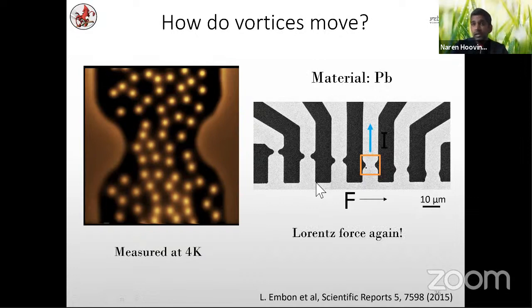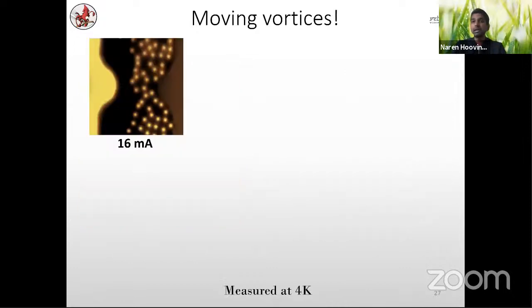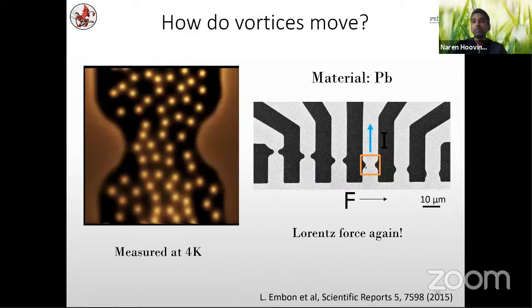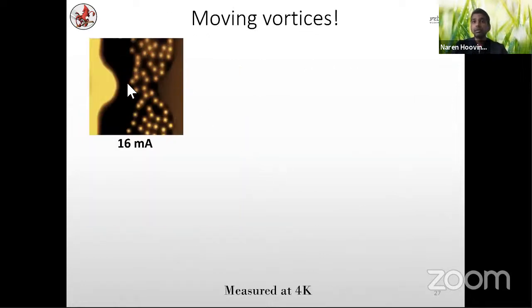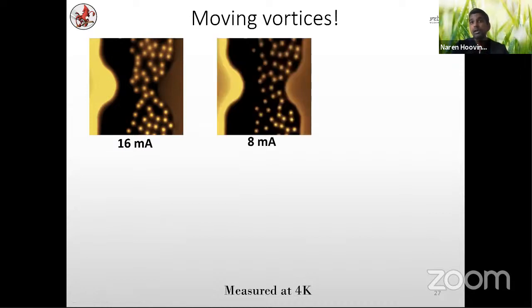And so then you need extra force. So there is a certain pinning force. You can quantify how much energetically favorable it is for a vortex to sit at a certain site by the pinning force. So basically, if you apply a certain current, you need to create enough Lorentz force for the vortex to be moved out of a pinning center and then move to the next one. So basically that's what happens in this experiment, where we apply a current as well to the static vortices. And you can see that the vortices start moving to one end. By that I mean they have enough force to jump from the original site to the next site and hold there. And then you can reduce the current and see what happens.